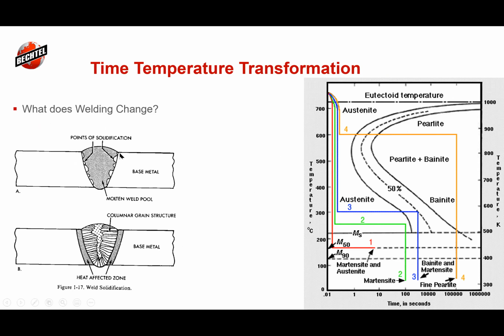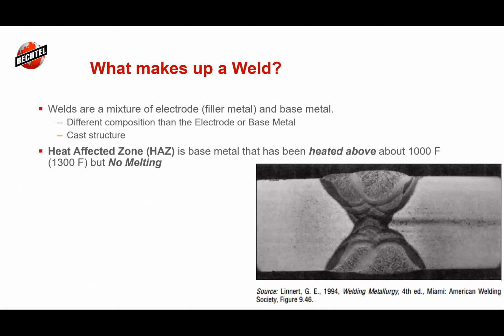When we're really close to the fusion line, we almost have that liquid. So we're raising the temperature way up, and now it's cooling down. But then as we step away, every point away from that heat affected zone is seeing a different maximum temperature. So it's almost like layers of an onion, where every layer of that heat affected zone is seeing a slightly different maximum temperature and then a slightly different cool off rate. So it's having a different time at temperature for each measure along that heat affected zone.